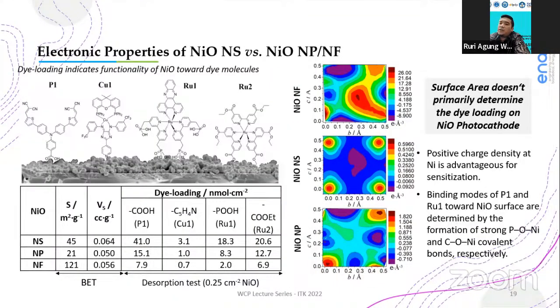And then we further examine the dye loading of different dyes using different anchoring groups, for example, pyridine, carboxylic acid, phosphonic acid, and try to correlate with the surface area of nickel oxide obtained from the BET measurement. So the dye loading here was estimated from the dye desorption test from a square nickel oxide electrode, and summarized in the table in the slide here. As we can see, the nickel oxide nanoflakes, which has the largest surface area, shows the lowest dye loading, while the nanostars, which has a moderate surface area, shows very high dye loading, sometimes 5 to 10 times higher than other nanostructures. So these results suggest that the surface area doesn't determine the dye loading on nickel oxide.